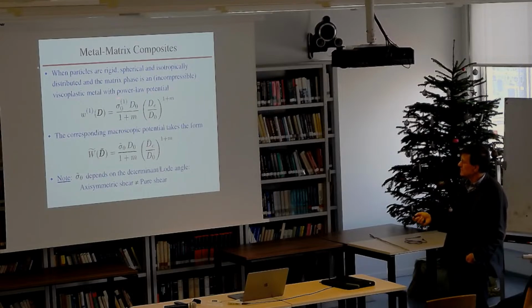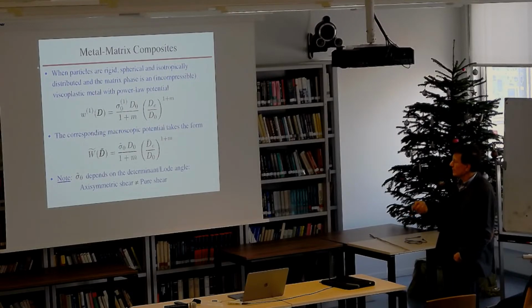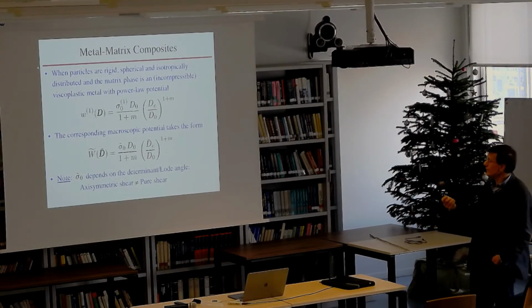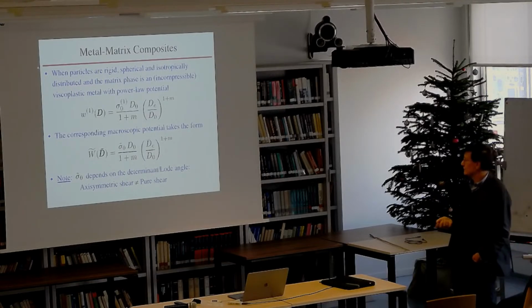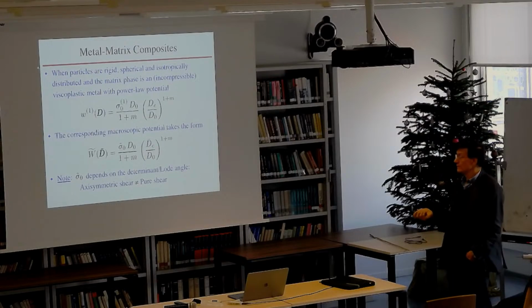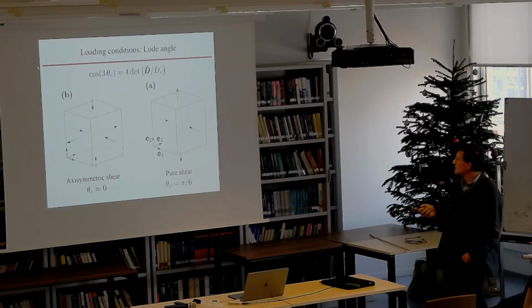And that is that this effective flow stress actually depends on the determinant. This is a linear material, incompressible, isotropic. You can only have dependence on the second invariant. But if you go to something that is nonlinear, in principle, you can have dependence on the third invariant, which is the determinant. So this tilde should depend on the determinant.